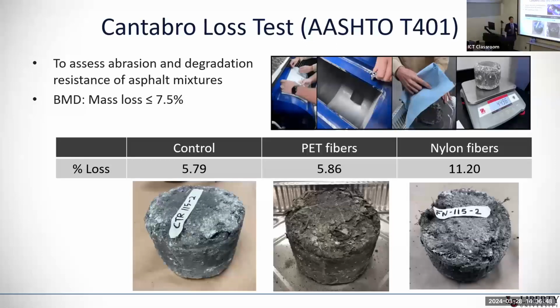What we observed in the lab is that as we add more and more fiber, the material becomes kind of softer and loose, and sometimes it's really hard to hold the shape of the specimen. So what we did is make a 115 millimeter height specimen, put it into this Cantabro drum, and rotate it without steel balls to see the durability of these specimens. The control mix shows a material loss of 5.8%, and the PET fibers have almost similar material loss, although in this picture we picked the worst specimen. And the nylon fibers, as you can see, are hairy, but it lost a lot of the material.